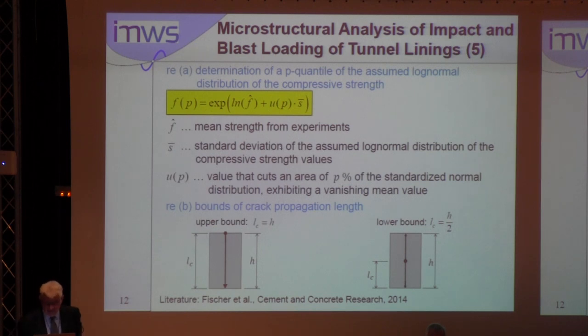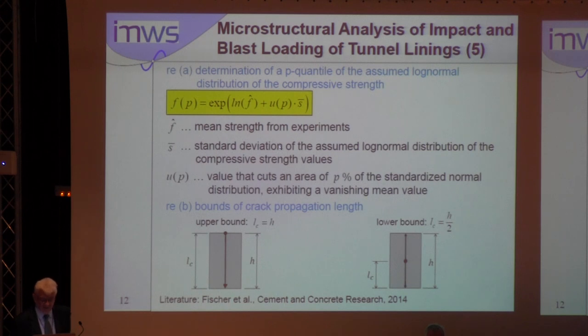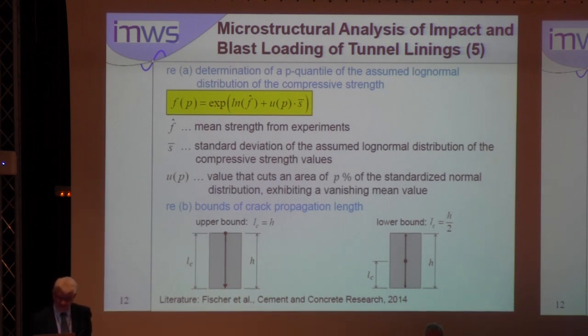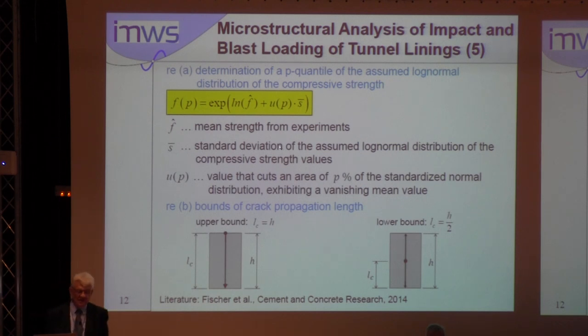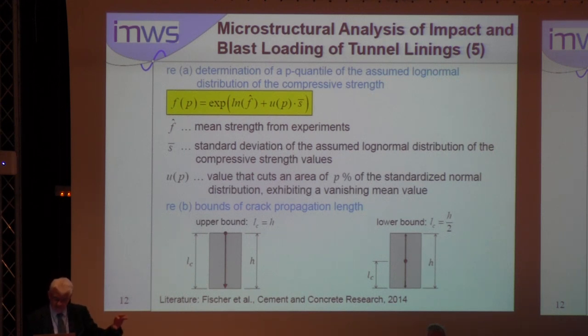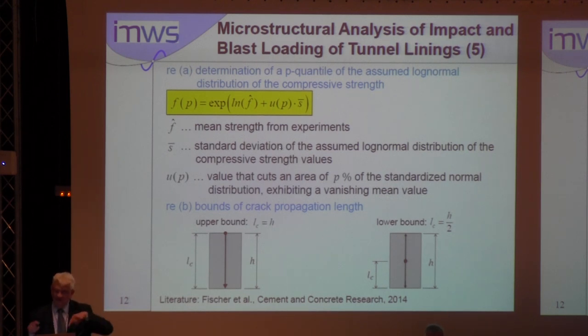This suggested determination of a p-quantile of the assumed log-normal distribution of the compressive strength. The respective formula contains the mean strength f-hat from experiments. s-bar stands for the standard deviation of the assumed log-normal distribution of compressive strength values, and U as a function of p is a value that cuts an area of p% of the standardized normal distribution. The two figures at the lower end of the slide refer to the bounds of crack propagation length: the left figure to the upper bound, assuming the crack starts at the top surface, and the right figure to the lower bound, assuming the crack starts in the middle and propagates in both directions.